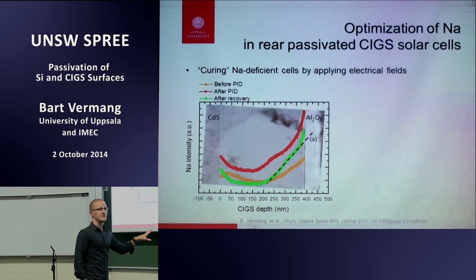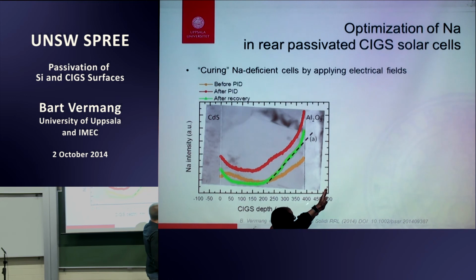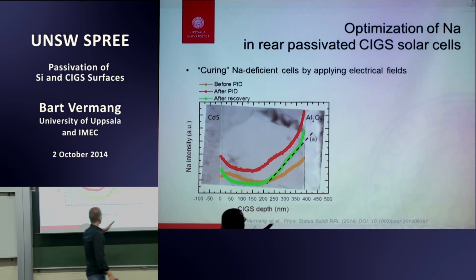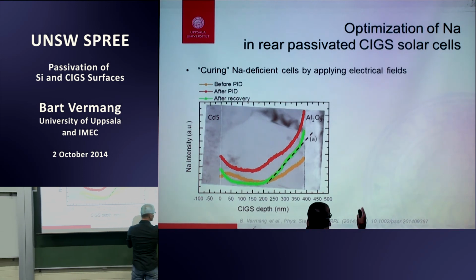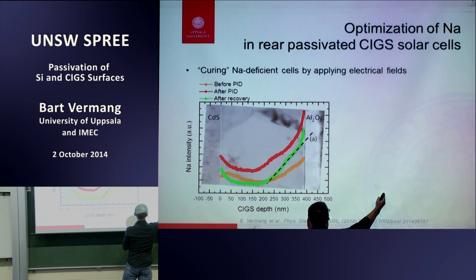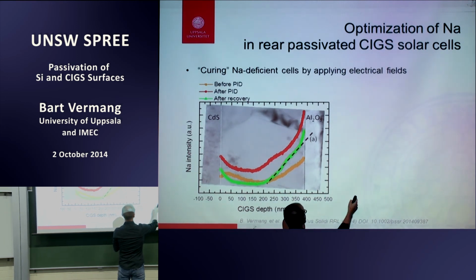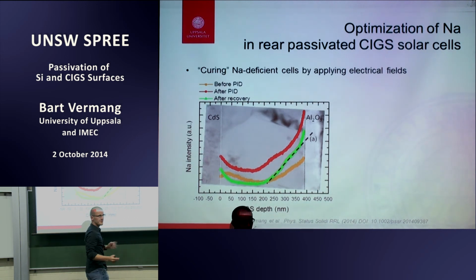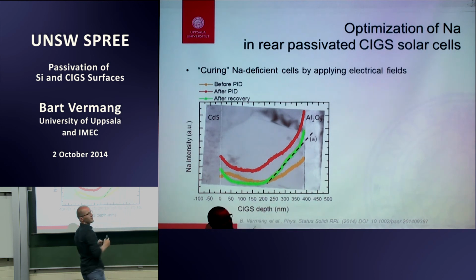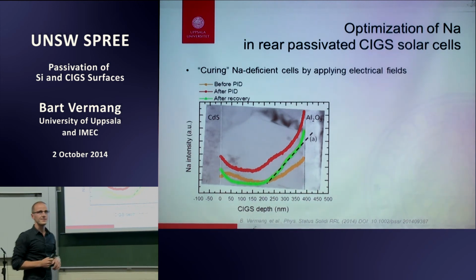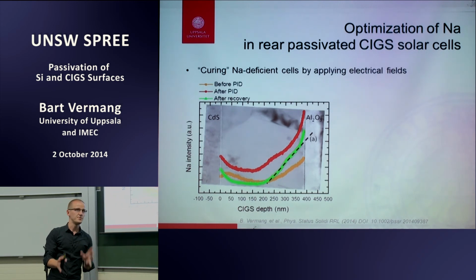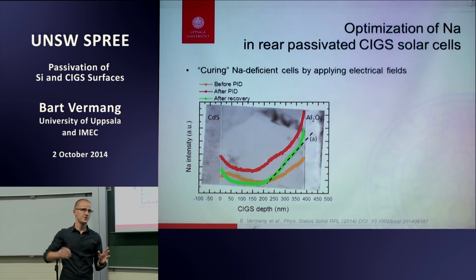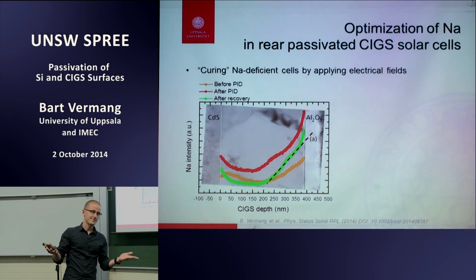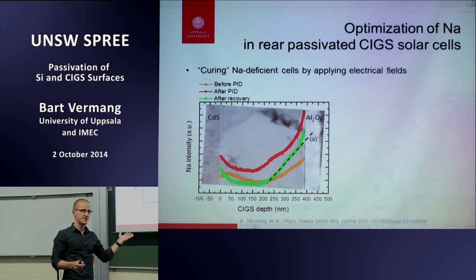But we don't use aluminum oxide as a field. What we do is put a cathode and an anode at the molybdenum, so we put an electric field between the rear of the glass and the moly. Then, by diffusion, we think, the sodium starts to move through the openings of the aluminum oxide. But we don't know if it's really diffusion or whatever. We see the sodium increases by having an electrical field between the rear of the glass and the molybdenum contact. So the sodium is coming from the glass through the molybdenum into the aluminum oxide? Yes. Not into the aluminum oxide, into the CIGS layer. We want the sodium in the CIGS layer.